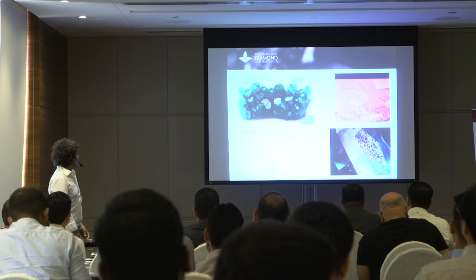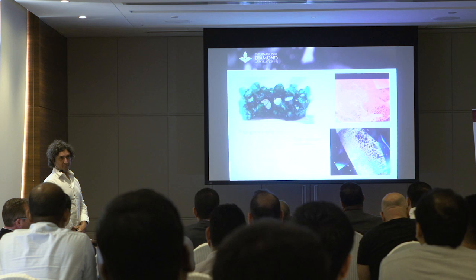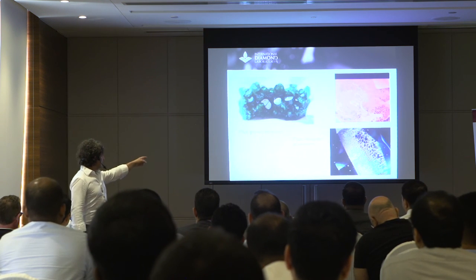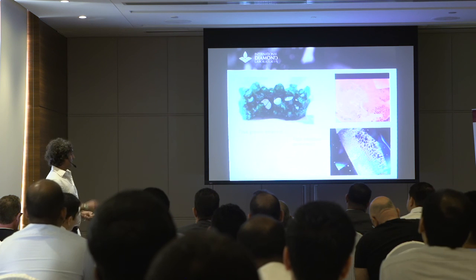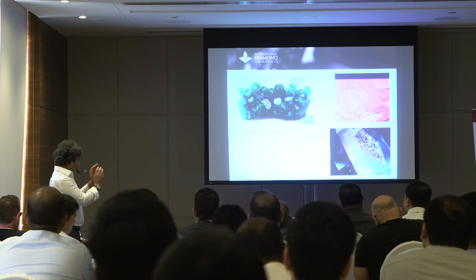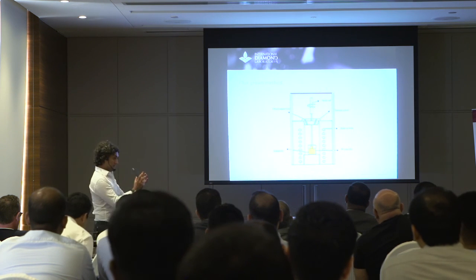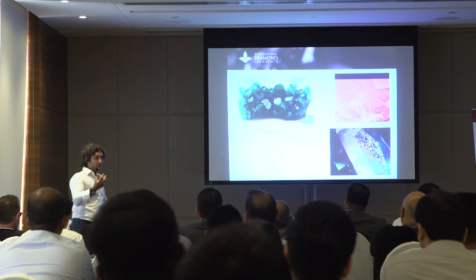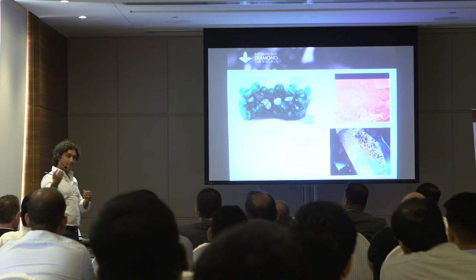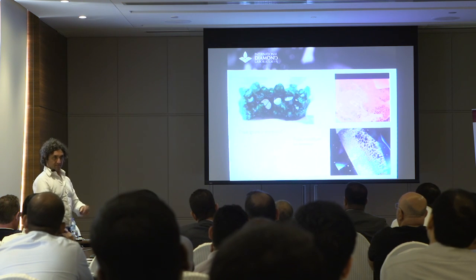And these are, let's say, typical inclusions to identify a synthetic emerald. Sometimes we even have small crystals of platinum, because the emeralds are growing inside a platinum kind of container. So part of the platinum goes into the process.